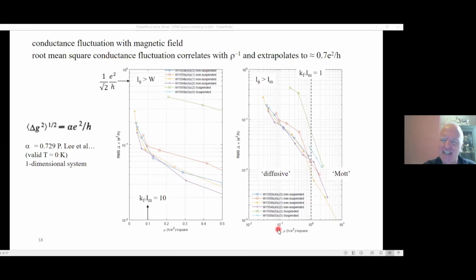Now it's slightly unphysical because the resistivity of the device really depends on the size of the device and the scattering mechanisms and so on. The root mean square conductance fluctuation does not depend on the scattering mechanism at all. It depends on temperature, but it shouldn't depend on the resistivity. However, there's several reasons. We're not at zero temperature. If we were at zero temperature, the situation might be different here. We're at finite temperature, and there is a relationship between the root mean square conductance fluctuation and the resistivity.